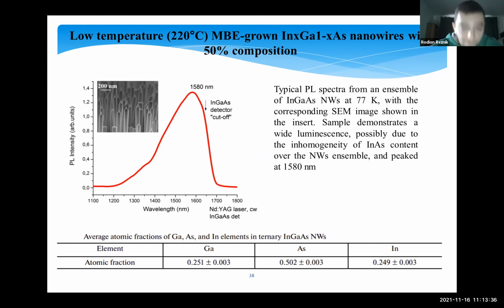So these are the results of our EDX measurements. We really have the same content of gallium and indium inside, but also have a not so simple structure, with a core-shell with different content of indium and gallium in the core and shell. And also Vladimir Dubrovsky has described this system.